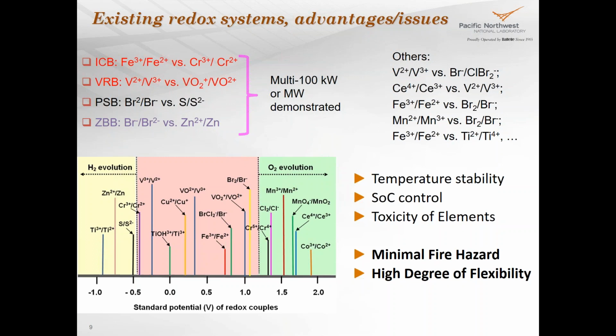Normally, the challenges of redox flow batteries are the temperature stability of the electrolytes. Also, we need to control the SOC to avoid gas generation. When the voltage is too high, we run into water electrolysis, which basically decomposes your solvent. Also, some of the elements have toxicity. We use a lot of acid, HCl, sulfuric acid. But again, the redox flow battery is relatively very safe without fire hazards, and there's a big degree of flexibility.